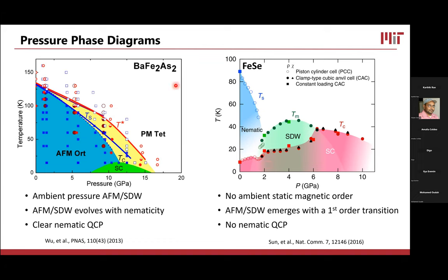I guess I skipped that in talking through the diagram, but on the barium iron arsenide side, when you get to the point of full suppression of the antiferromagnetic and nematic phases, you reach the general area of maximum superconducting transition temperature. So that leads to this really nice idea that seems to work very well of nematic quantum criticality. On the iron selenide side, you don't see the peak of the superconducting transition in the vicinity of this suppressed nematic phase. So it seems like it's a more complicated story here.